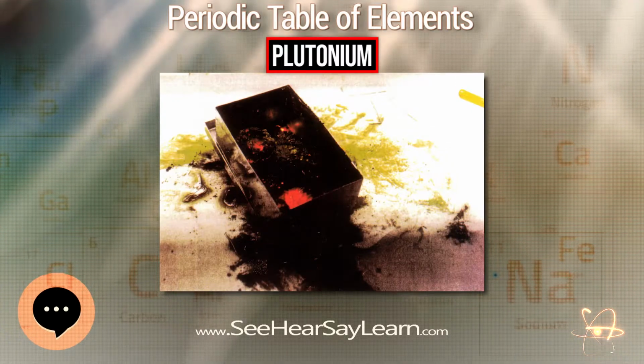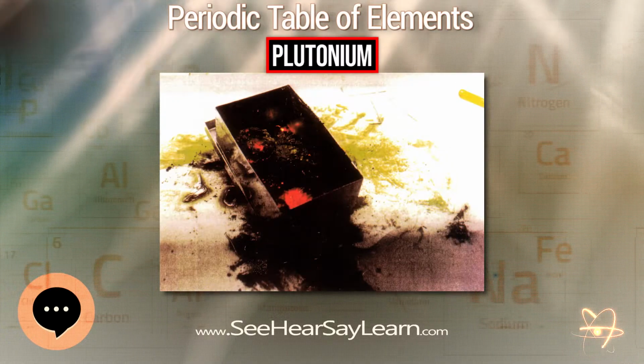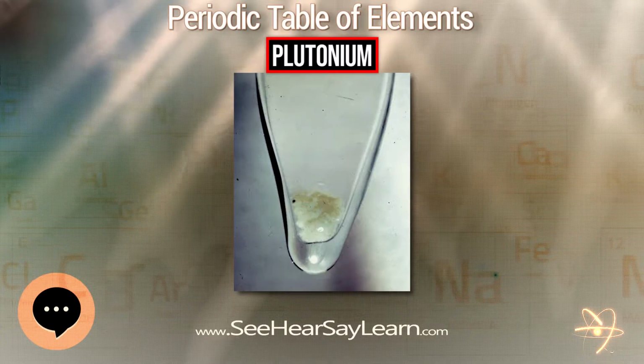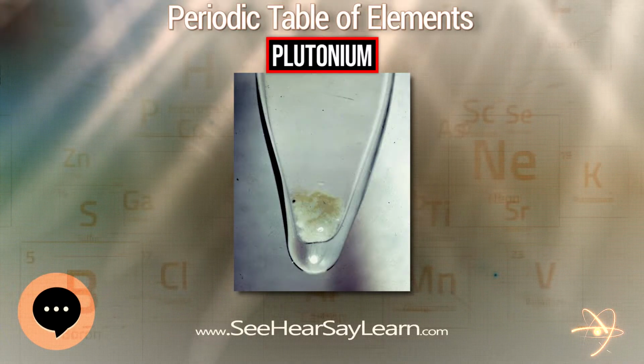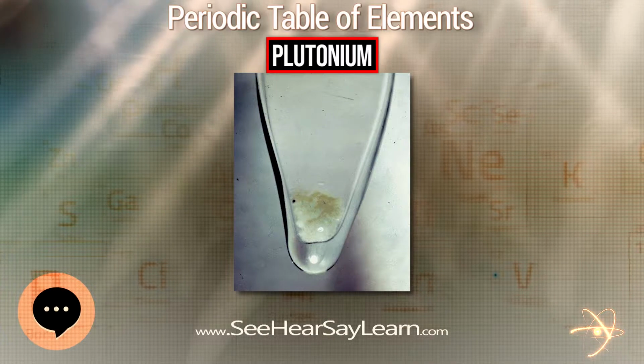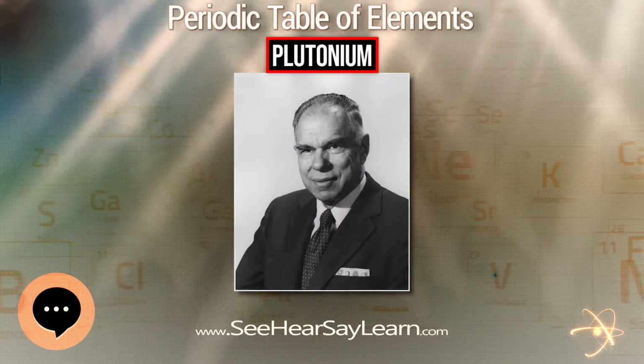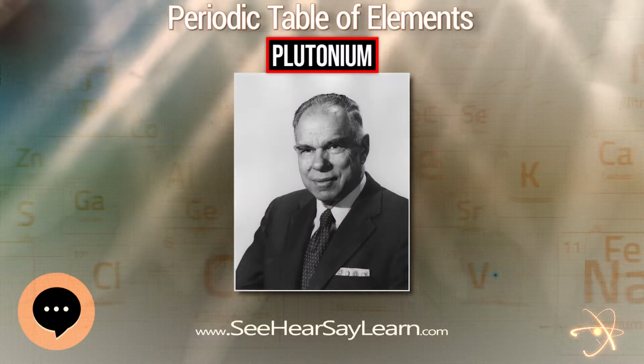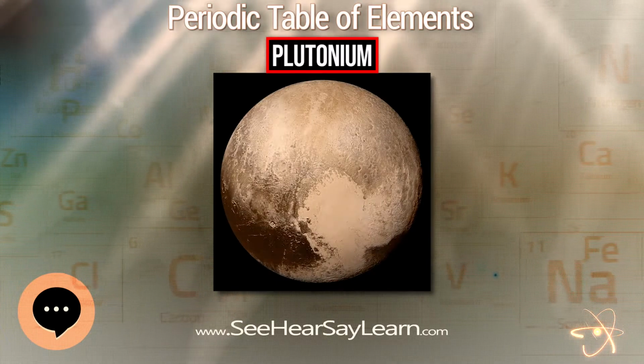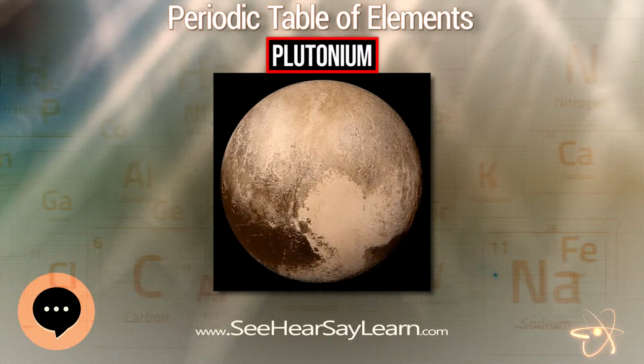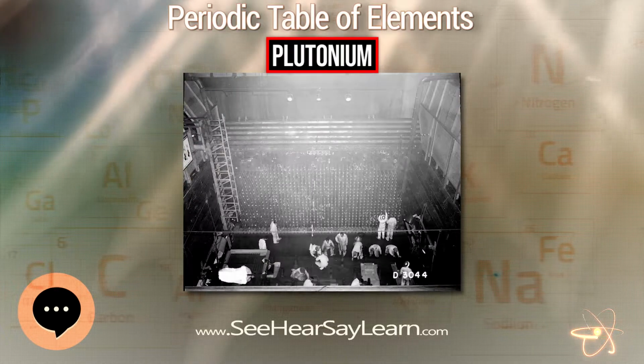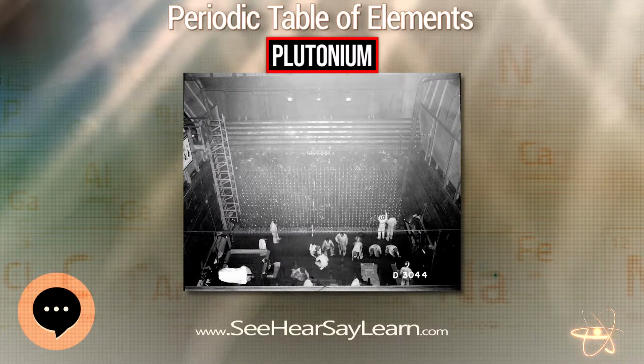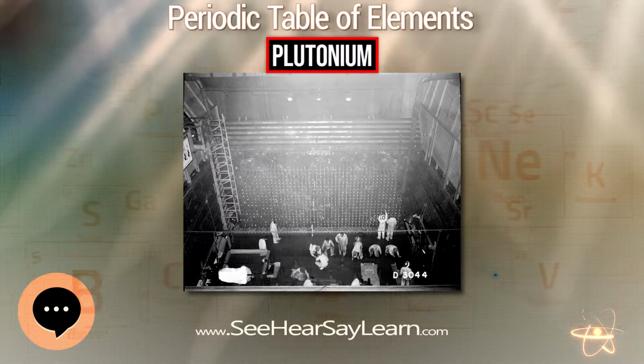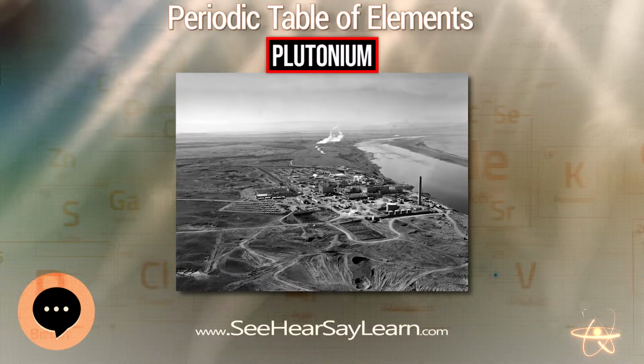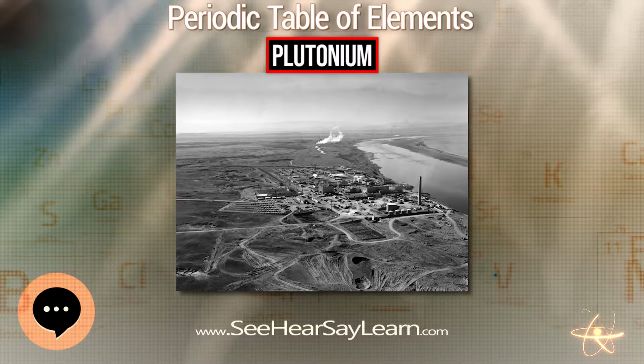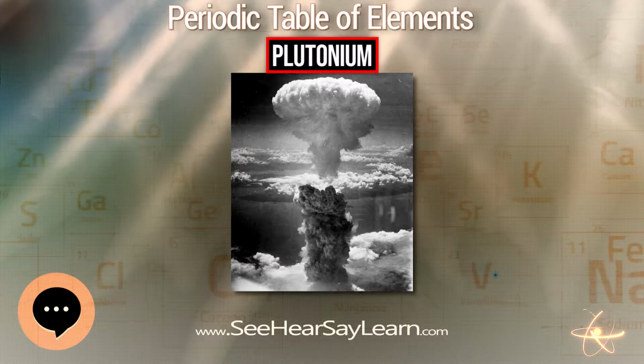Resistivity is a measure of how strongly a material opposes the flow of electric current. The resistivity of plutonium at room temperature is very high for a metal, and it gets even higher with lower temperatures, which is unusual for metals. This trend continues down to 100K, below which resistivity rapidly decreases for fresh samples. Resistivity then begins to increase with time at around 20K due to radiation damage, with the rate dictated by the isotopic composition of the sample.